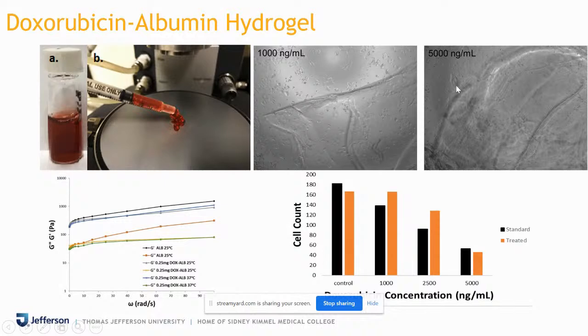You can see over here the background of this inverted microscope image, where you can see the background of the gel, and the dots that you see are the cells dying because of the drug which is present in the gel. This is 5,000 nanogram per ml, and this was 1,000 nanogram per ml. At 1,000 nanogram per ml, you can see the cells are still alive, and they have colony structures over here. They are still dying, but it's not efficient enough, which is in line with the live cell assay that we did over here. So we have both visible observation as well as the cell cytotoxicity assay that could confirm that the albumin gels are an interesting personalized delivery system, nanodrug delivery system.